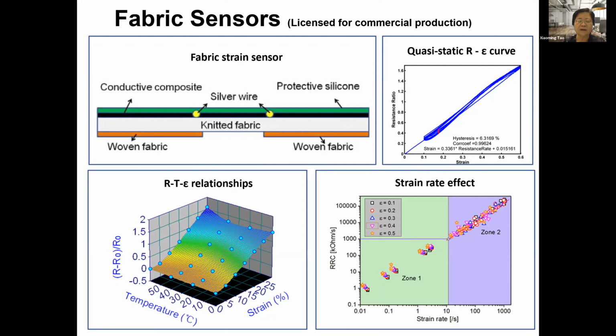And this fabric sensor has a very nice response in the composite state. The relative change in the resistance is almost linearly proportional to the strain level. And the temperature is not that sensitive. If the change in temperature is less than 10 degrees C, we probably don't need compensation. Therefore, it lends itself to being a very good wearable sensor. And people may ask, what is the effect of moisture? It has no effect. So this is quasi-static.